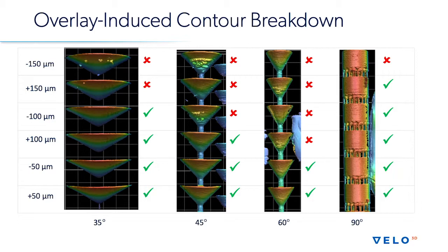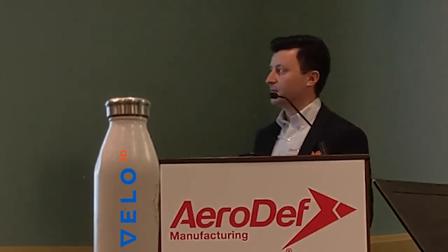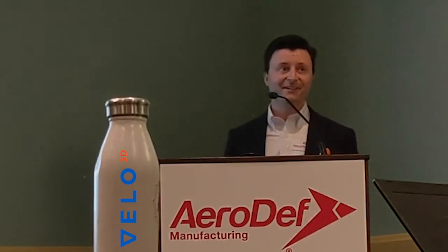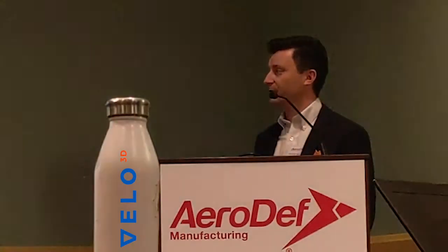And we have a number of other tests. We've established that a 50 micron offset in overlays is generally good enough in terms of porosity, in terms of mechanical properties, in terms of the surface roughness. So 50 microns is the spec that we set as an acceptable limit. That doesn't mean that you shouldn't try to do better, but 50 microns is a good place to be.